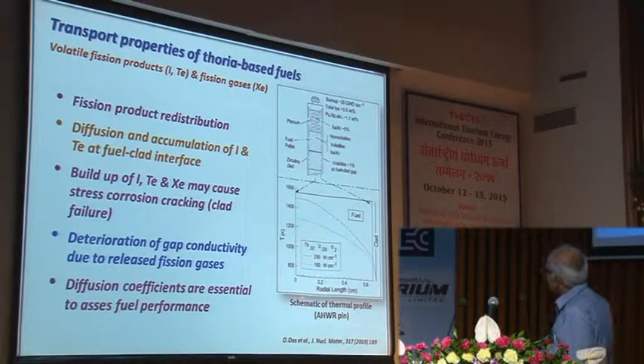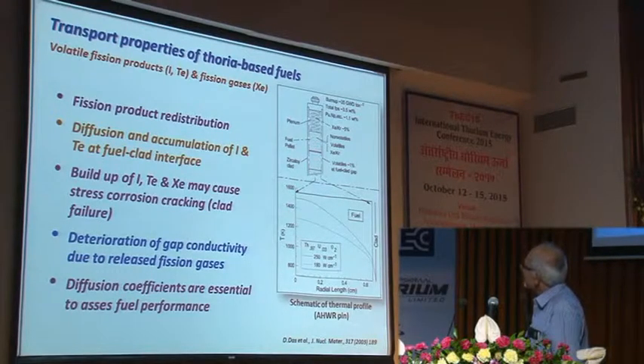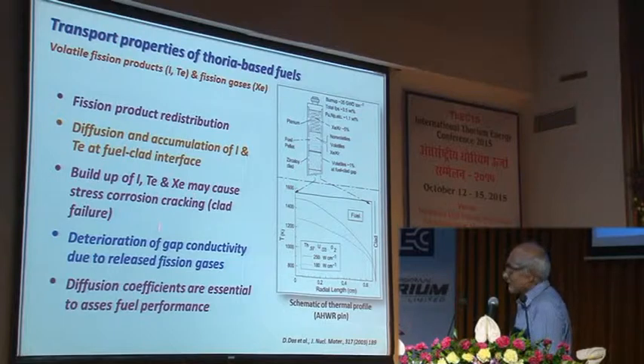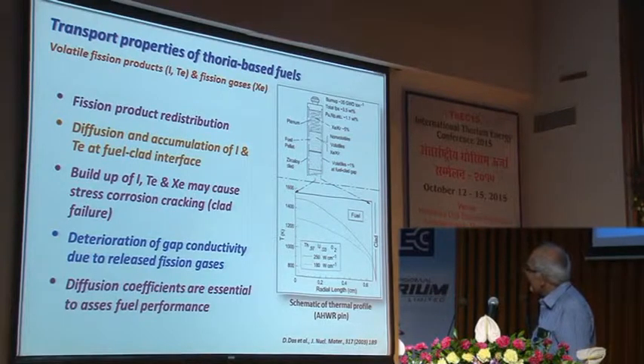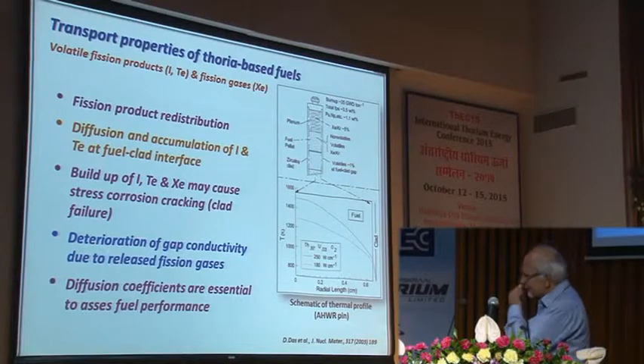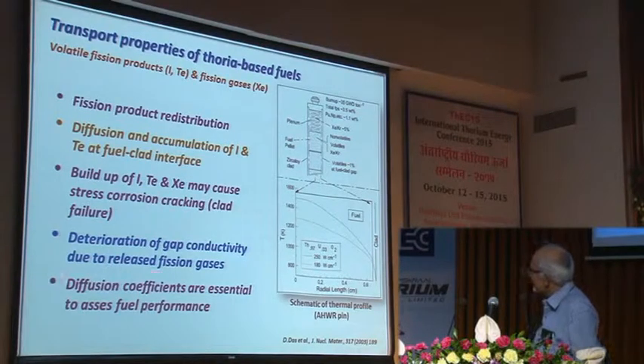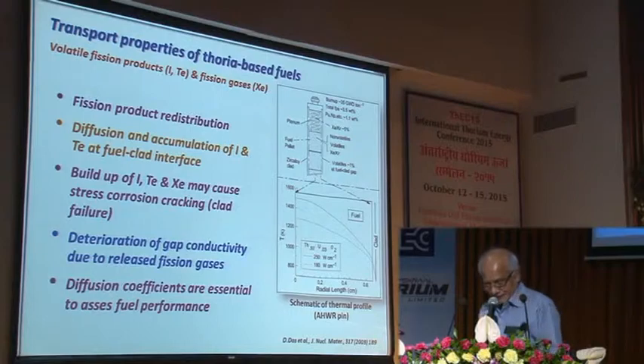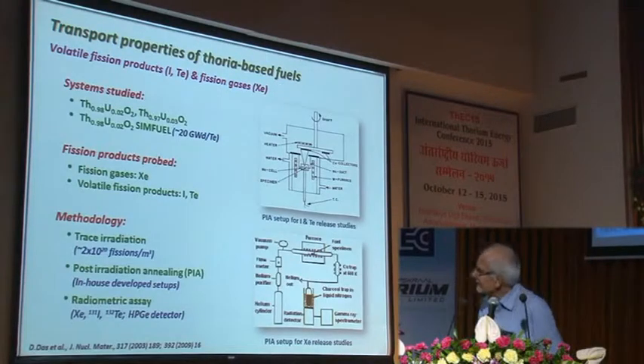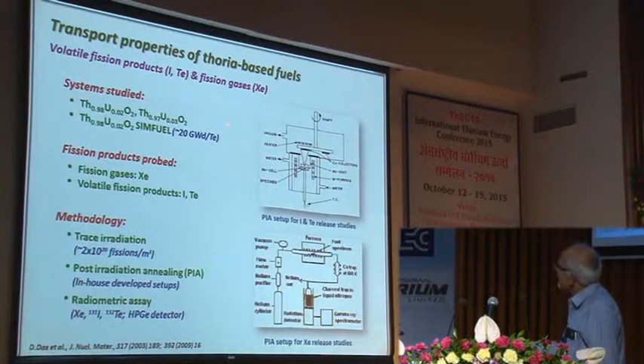For example, this is a typical schematic thermal profile of an AHWR pin, and you can see the temperature variation from here to here. This is the fuel pellet, and this is the zircaloy clad there. So the diffusion and accumulation of iodine and tellurium at the fuel-clad interface, and the buildup of iodine, tellurium, and xenon, can cause stress corrosion cracking, and also deterioration of the gap conductivity due to released fission gases. Therefore the diffusion coefficients become very important inputs for this. And in this case, we have studied these fuels.